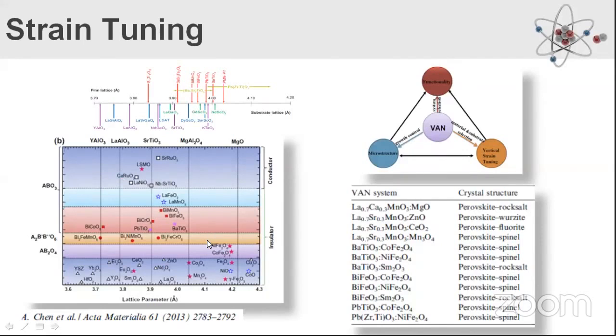You can grow these materials epitaxially on these substrates, whether you need a conducting material, an insulating material, or a magnetic material. As I mentioned, the strontium titanate lattice parameter will be around 3.9. If you want to put a tensile strain, you can use either MgO or magnesium aluminate substrate, which have a lattice parameter around 4.1 or 4.2. If you put bismuth ferrite, for example, which has a lattice parameter of 3.9, on this substrate, it will have a tensile stress. On the other hand, if you put it on the lanthanum aluminate substrate, it will have a huge compressive strain.